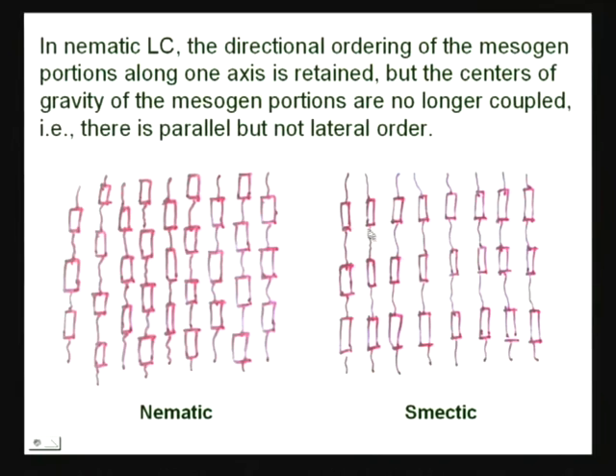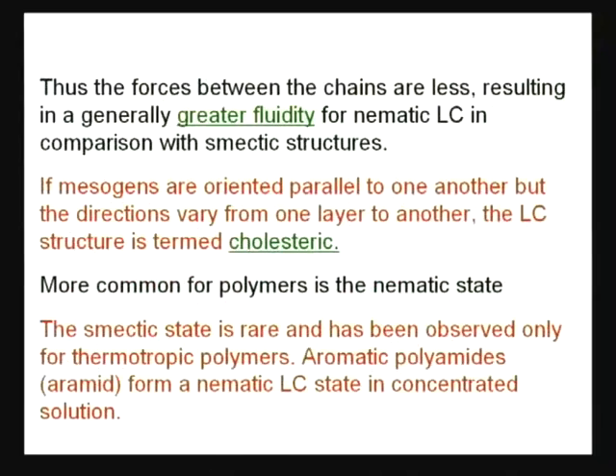Here you see all the mesogens are in one line almost. So, they can have interaction between the mesogens, and that can provide more or closer packing, closer interaction, stronger will be the material, either in fiber or in film form or in molded form. Thus, the forces between the chains are less in case of nematic, resulting in a general greater fluidity for nematic LC in comparison with Smectic structures.